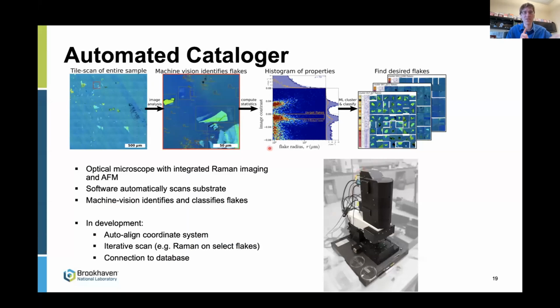Okay, so that was step one, robotic exfoliation to make flakes. And then you end up with these flakes on a substrate. Of course, by eye, it's really hard to tell whether it worked or not. So what people typically do is they go to an optical microscope and search around manually and hope they get lucky and find a flake that has the right thickness, the right size, the right shape.